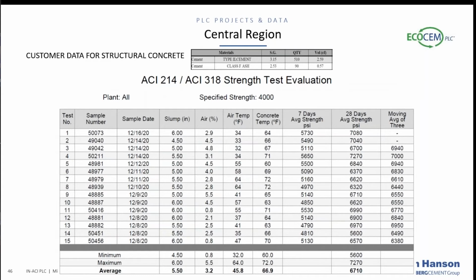Have a customer in the Central region that is providing concrete for structural work. This concrete does have 510 pounds of our type 1L cement with 90 pounds of an F-ash. And so what you can see here is that the strength performance has been outstanding. At 7 days, they've had some terrific values, 5,000 plus in almost every case. And the average for the 28-day data is 6710. The interesting part to me is that some of this has been at some cooler temps, anywhere from low 30s to mid 60s, without any adverse performance effects, and we're seeing the slump and things like that hold very steady.